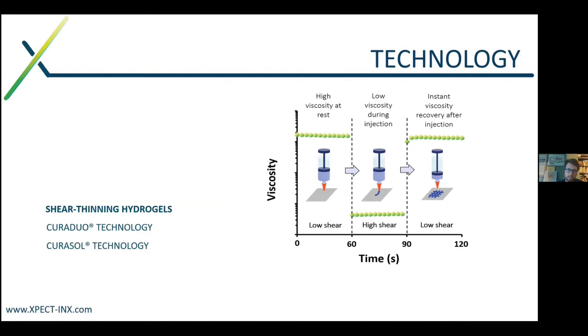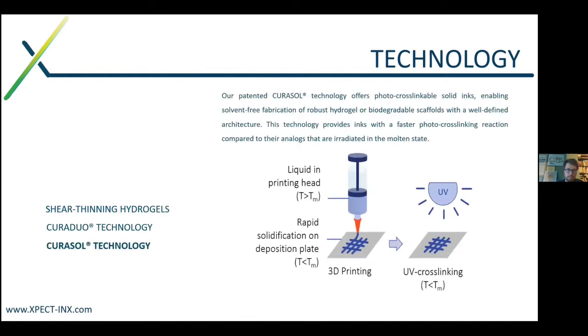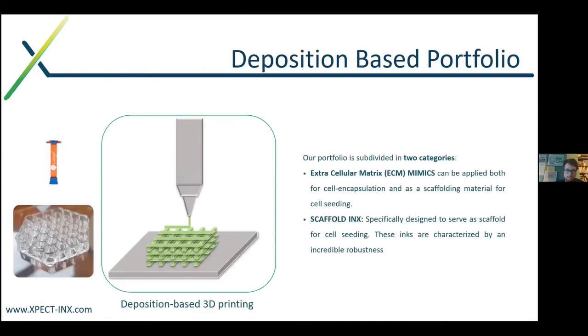Now, a next strategy to have this is to print materials directly from the melt. And therefore we can rely on one of our patents, our Curasol technology, which enables photocrosslinking of material in the solid state. So therefore we are able to print a hydrogel as a solid and then let it swell afterwards in water, making it the only hydrogel which can be printed in such a fashion. So we built a portfolio around this, which can be divided into two categories. So our first materials are what we are calling our extracellular matrix mimics. These are materials which are suitable for cell seeding, but can also be used for cell encapsulation during 3D printing. And then a second class are scaffoldings, which are only suitable for seeding after printing. And these are typically the materials which are printed from the melt, because of course you cannot blend cells in a molten polymer.